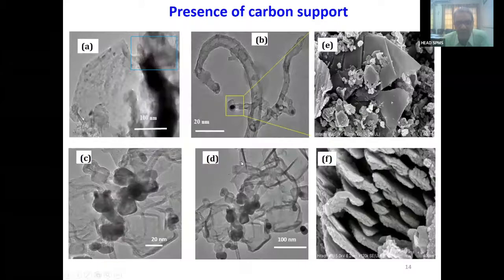Now, among the different structural features, the formation of carbon nanotubes also becomes important here. These features I have already enlarged in the next one, but you can see these bending phenomena, where inside the carbon nanotube some carbides are encapsulated. Second structural feature: you can see that this carbon nanotube forms from the graphite structure. This graphene is rolling out. You people might have seen the onion.